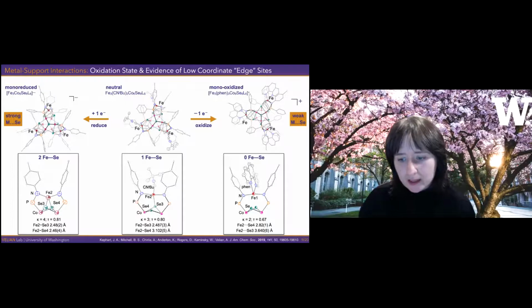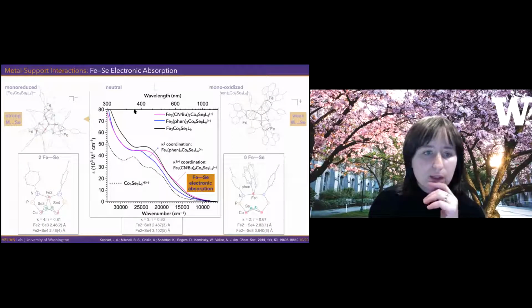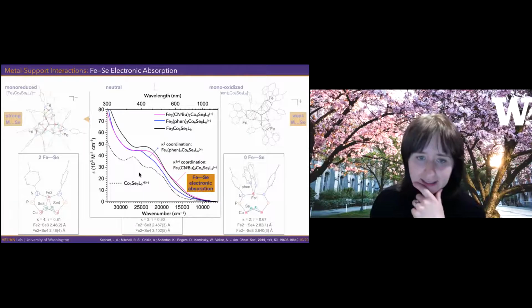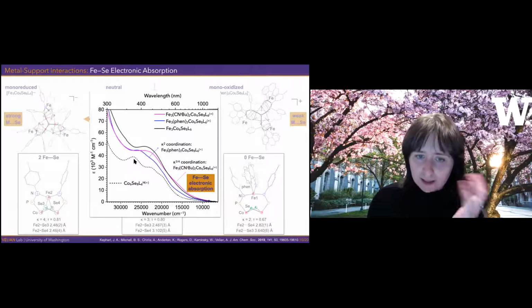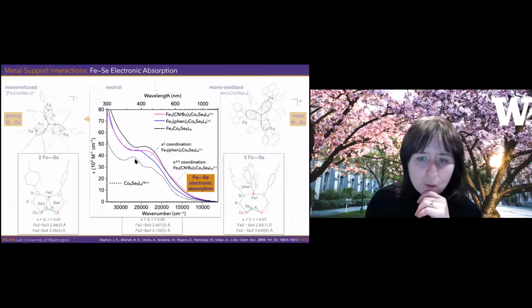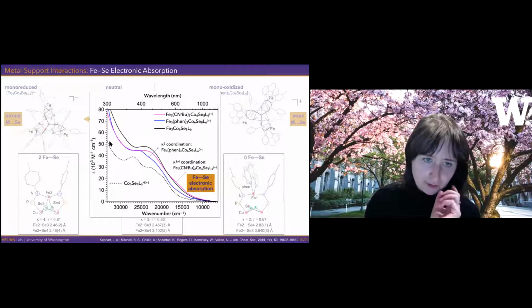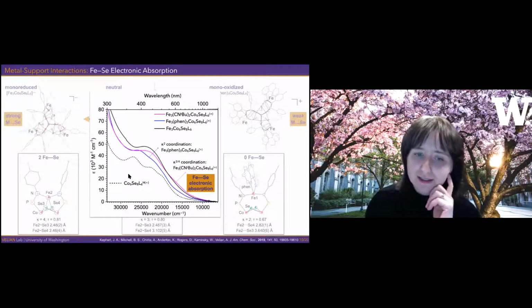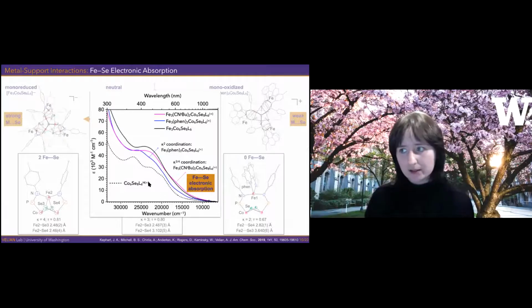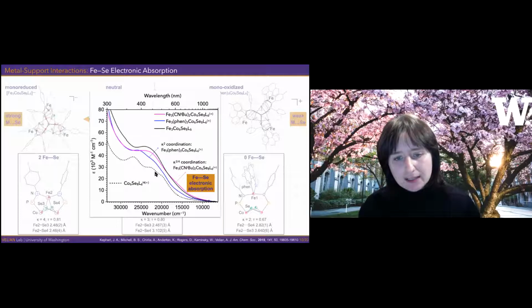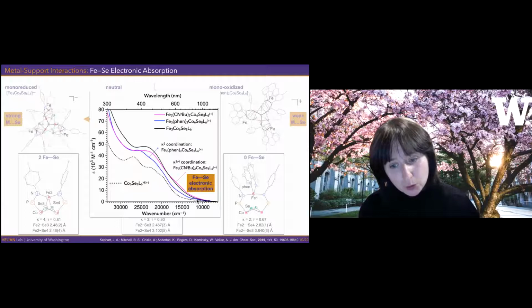And so, to probe that in a little more detail, we can, for example, start with UV-Vis spectroscopy. That's a nice way to probe any electronic transitions that occur. And what I want to draw your attention to in this plot is the following. In the dashed line, what we have is just the cluster, the cobalt selenide cluster without the edge sites, no irons. And then if we add the 3 metals, we see this increase in the absorption, and also a red shift and this absorption tail.